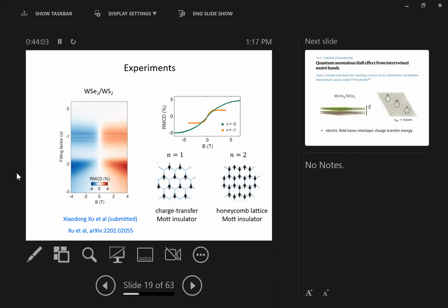That still leaves us with a magnetic moment at every site. In fact, there are more local moments than before, and that's why the circular dichroism signal is even stronger. Okay. So this also means that anywhere in between filling factor 1 and 2, the doped charge transfers to another sublattice. So an n equal 1 insulating state is a charge transfer insulator.